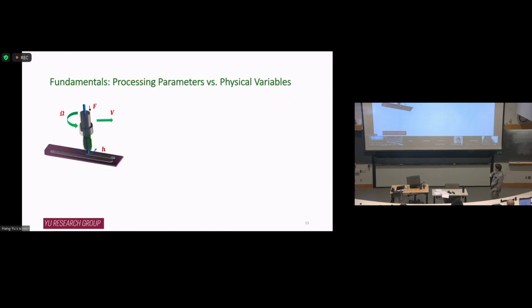Right, so like all the additive manufacturing processes, we have processing parameters, right? For a laser-based process, of course, the laser power and the scanning speed are the major parameters. In our case, one major parameter is the rotation rate, how fast you rotate your printing head, right? Because that's going to have a significant influence on heat generation. Another thing is F, which is the feed rate, how fast you feed your feedstock. Velocity, V, how fast you move your printing head. And finally, of course, the layer thickness. All these things will affect the physical conditions in this process. So those are the empirical processing parameters.